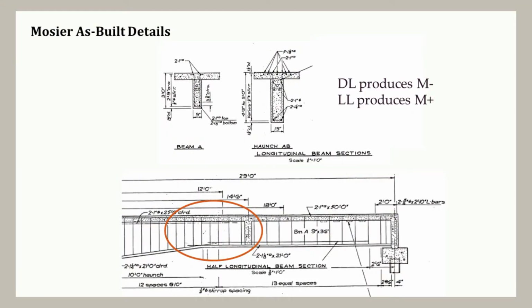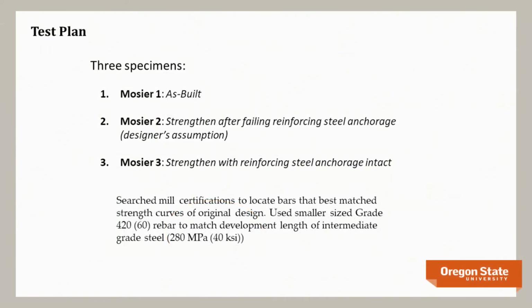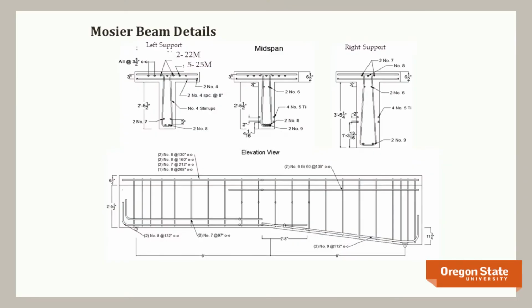We built three replicate specimens. One to look at what the behavior would be if we did nothing. Two, we actually said, let's fail the girder, because that's what the designer thinks has happened, that the girder has failed in place, so it has no reserve capacity at all, and we have to get the repair to do everything. And the third one is, well, there's probably some strength there, so let's not fail the girder. We'll just build a girder, add the repair, and see what happens. We really cherry-picked mill certs to make sure we could match the bars to the actual capacity. It's a funky girder, with all kinds of geometric problems and changes, so we tried to build the best replica we could at full scale.